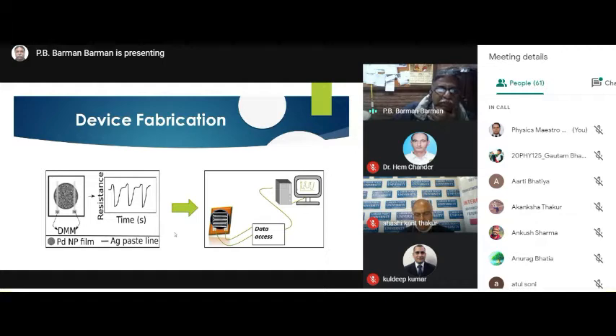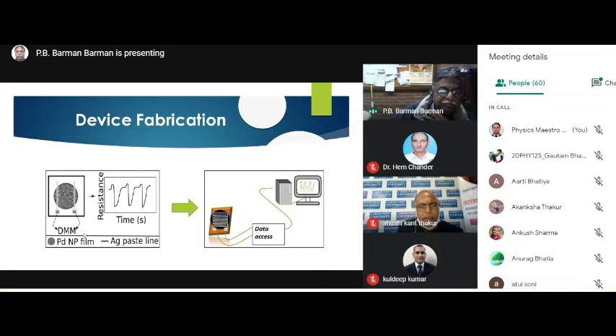Finally, we went for device fabrication, and this is a very simple device fabrication. This is just a silver lining. You can see over here the palladium nanoparticles, and we have connected the digital multimeter. We have just a film on my glass surface, and this is practically the silver film or silver paste, and this is the response time setup. This is a very simple experiment we have done, and anybody can do it in his lab, even just a BTech or BSc lab.